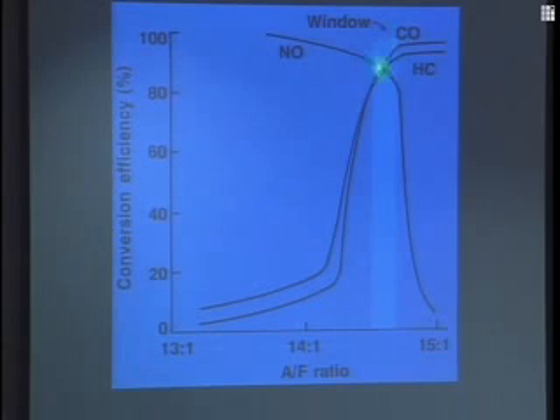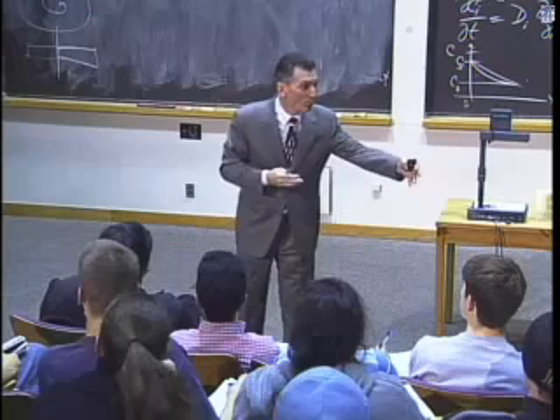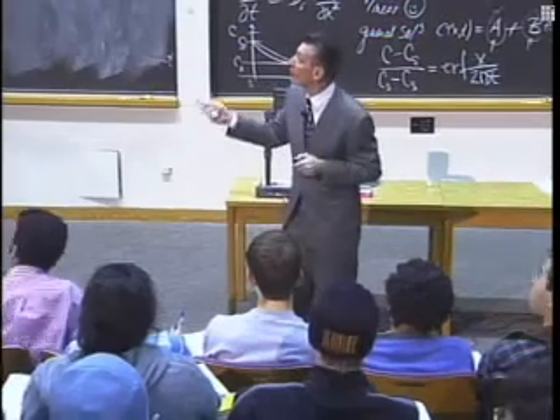And the catalyst is pretty good at very, very high air ratios. And to reduce NOx to nitrogen, you need to have rich fuel ratios. And mercifully, nature was kind, and there's this tiny window at about 14.6 to 1 where you get fairly high yields on both catalytic reactions. So this is where you want to park yourself.